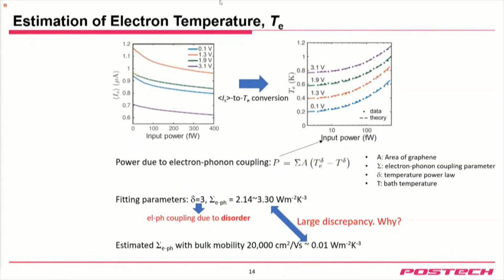Okay, so by using the information of the power dependence of the decrease of switching current and the temperature dependence of the switching current of the Josephson junction, we can reconstruct the electron temperature of the graphene as a function of input microwave power. And this can be easily fit by the electron-phonon coupling, because our situation is the following. We continuously input microwave into the graphene, and that power is continuously dissipated by electron-phonon coupling. This equilibrium makes the electron temperature reach some equilibrium temperature. That is exactly what we are measuring here. By fitting this, we can infer the electron-phonon coupling sigma value, which is about this. But this electron-phonon coupling is like 100 times larger than the theoretical value.